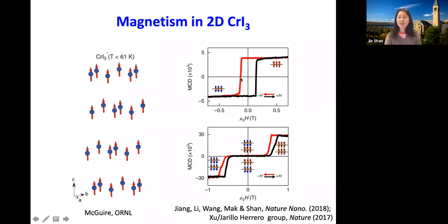And what's surprising is that when you have 2 sheets of those materials at zero field, you actually get a 0 magnetization. And if you apply something around a half Tesla, then suddenly you turn on a large magnetization. And then when you reverse the field direction, you get a hysteresis and then go to the other direction. So this tells us that the bilayer actually is an antiferromagnet, and those are 2 possible spin alignments in the 2 layers. And this is something people refer to as A-type antiferromagnet. So 2 different layers, antiferromagnetically coupled ferromagnetic layers.